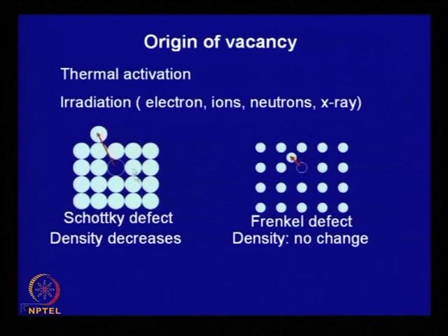So, looking at this mechanism of formation of vacancy, one way of measurement could be density. Similarly, there will be some changes in lattice parameter, as the dimension also can change. So from X-ray, by calculating the effective lattice parameter, you will also get some idea about the vacancy concentration.